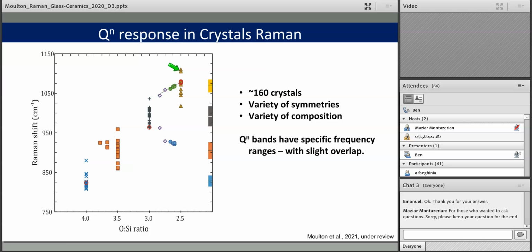And we see that there's the same frequency shift observed for the 160 crystals, but for a much larger range. And I've given some bounds on what the expected values are. There is a little bit of overlap you can see between the extremes of these frequencies, but there is quite a systematic trend that can be found if one looks closely enough.